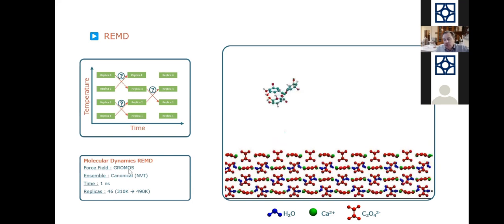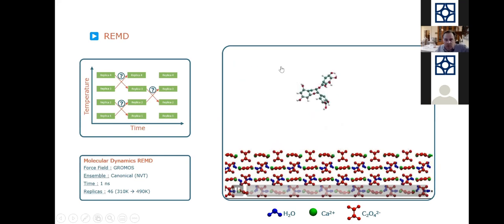So here again, we use force fields in order to do it faster. We don't use DFT molecular dynamics here. It's again canonical, 1 nanosecond, and we have here 46 replicas. We also have to introduce some differences in temperature, because we need to cross some barriers. So in order to obtain a geometry, we have to use this technique. You see the molecule is jumping, and this means every time it finds a more stable geometry, it jumps there and then it's there. It will be more and more present at the surface. So in fact, you accelerate your search for an adsorption geometry.